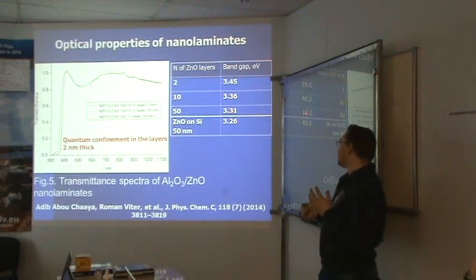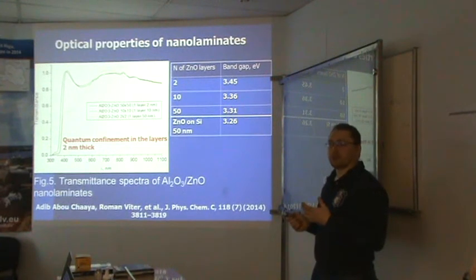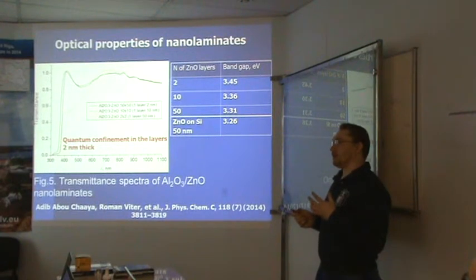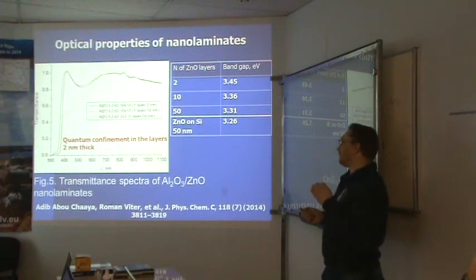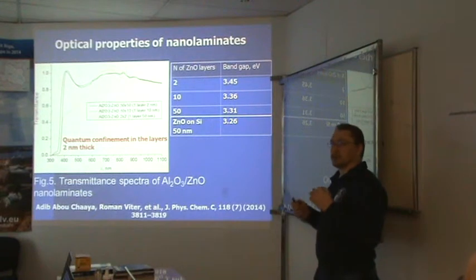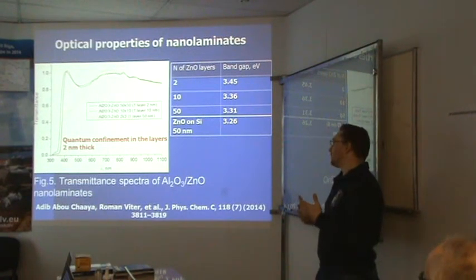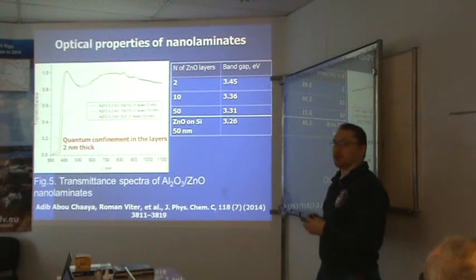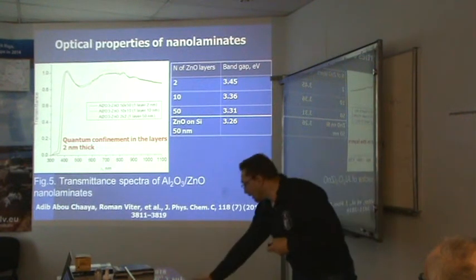So it resulted in the growth of the band gap, and it was proportional. We had a dependence that the lower the grain size, the higher the band gap, and it was in good correlation with the quantum confinement effect theory for these nanostructures.